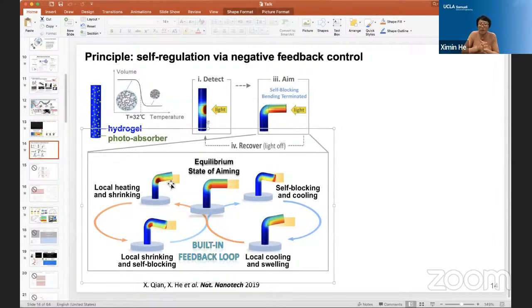However, there are many different ways. For example, by adding a bilayer or passive layer, or maybe a middle layer in a sandwich structure, as we show in some of our other work, we can address this issue, so that it can probably make this length scale even broader, down to real nanoscale. So all these are potentially possible, right? And we have this multi-physics model to help guide the design, how small or how large we can make it. Yeah. Thank you.